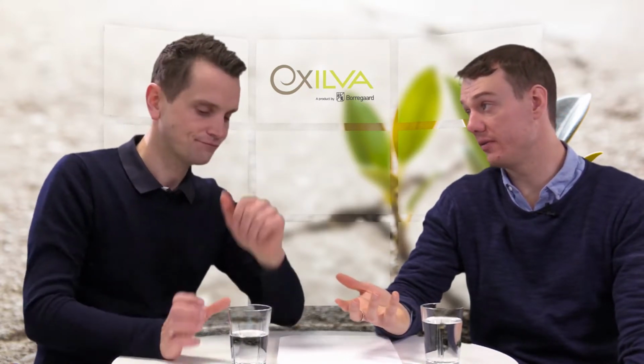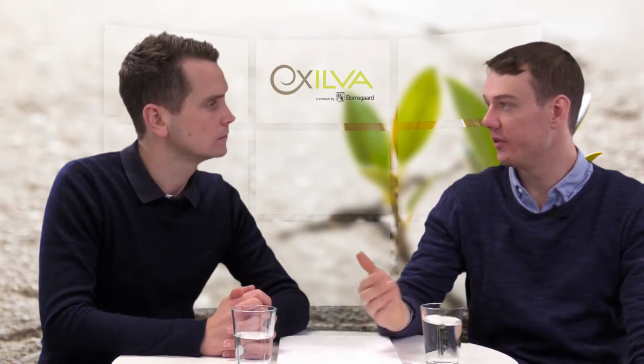Some are synthetic, so again, petrol-based, not ideal. You have glass fibers, but they have reduced strength. They're not good at keeping the compressive strength of a material. Steel fibers rust, so they have a short lifespan. And the natural fibers are very good, but they're hard to pump. They're not the easiest, and you have to have a lot of machines to help you pump the material with the fibers in place.